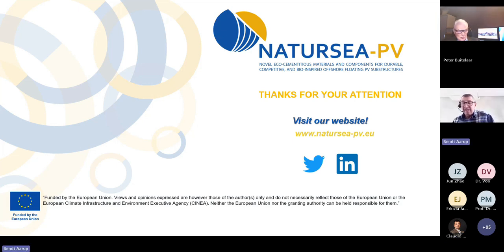No, it's not. It's based on the ETA and the EAD that we developed, and this is in the European EOTA system, which means that every European country has some agency that has approved this ETA. In Germany, it's DIBt. In Sweden, it's RISE, for instance. And when we have this ETA, then we get the CE marking based on normal certification, like a normal precast company would, where they come out and see, do we fulfill all the normal requirements for concrete according to EN 206 and the special requirements that are stated in the ETA. And then based on this, we have a certification.